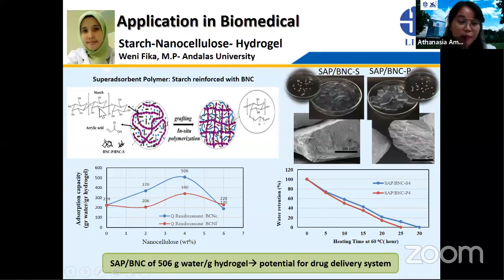The second hydrogel production that we have explored is based on starch polymer. We use starch as the main backbone to substitute the monomer of acrylic acid. We also incorporated bacterial nanocellulose, both from sulfuric and phosphoric acid hydrolysis. You can see that the presence of nanocellulose in the starch-based hydrogel gives a significant improvement, from 200 gram water per gram hydrogel to double, 500 gram water per gram hydrogel, which, when you remember my previous slide, reaches the optimum for a potential drug delivery system.